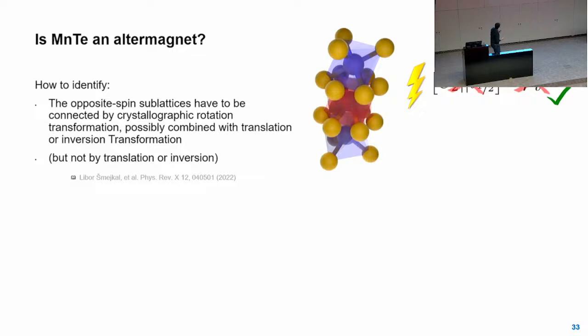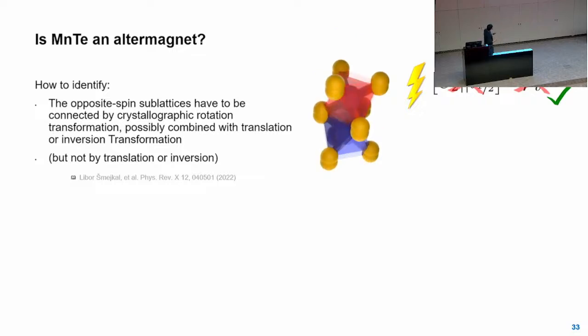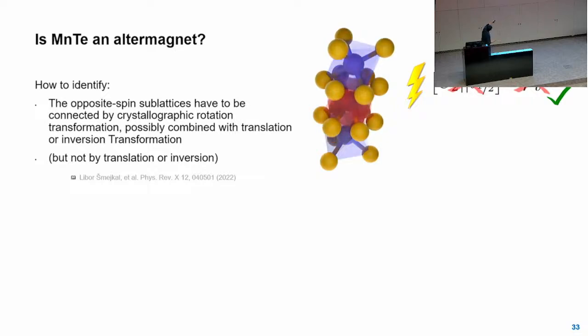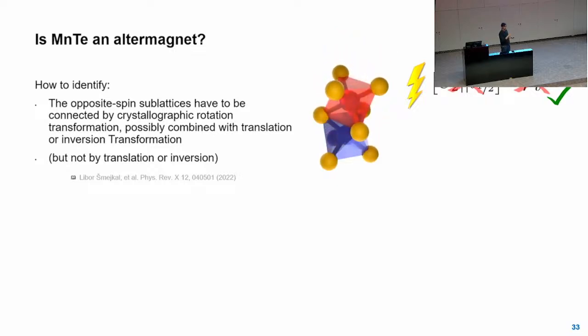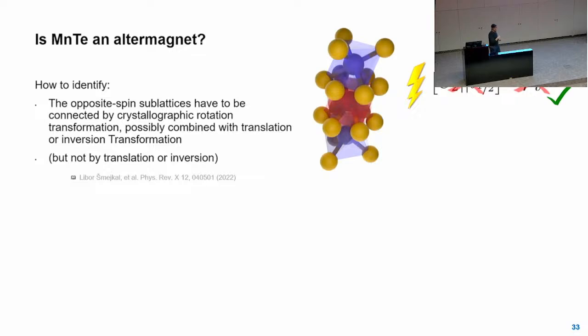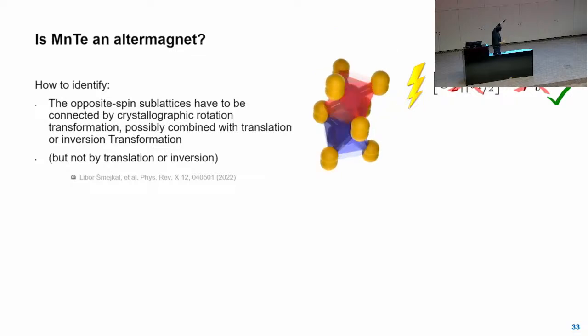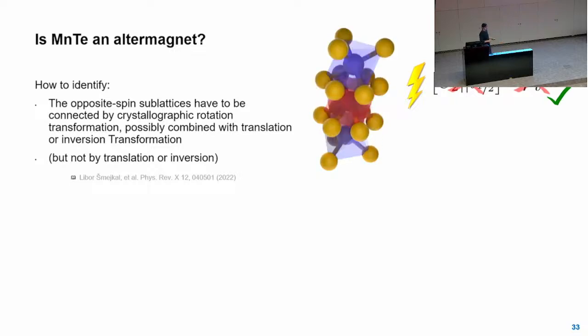So let's try the pure translation as an example. So let's move the blue up to the red. At the same time we change the color. This means we translate it and we apply the time reversal symmetry operation, exactly like we did before for the 2D cartoon. And you see, okay, the magnetic atoms, they overlap, but we have a problem here. We see that the non-magnetic atoms, they're actually not overlying. So we clearly see that this is not a symmetry operation. So this means that we can basically already exclude that we have an antiferromagnet. It's magnetically compensated, but it's not an antiferromagnet. Antiferromagnets must have this symmetry operation.